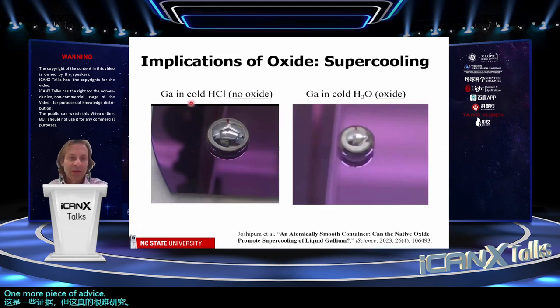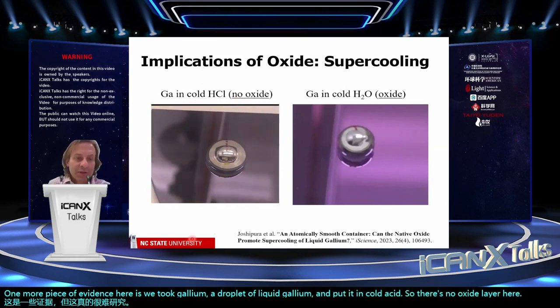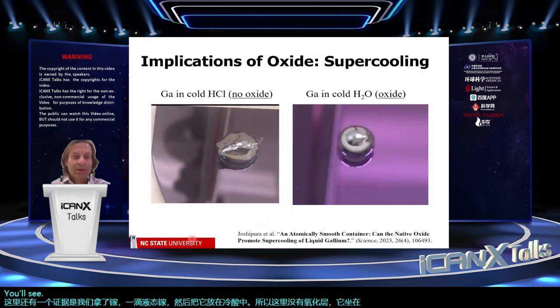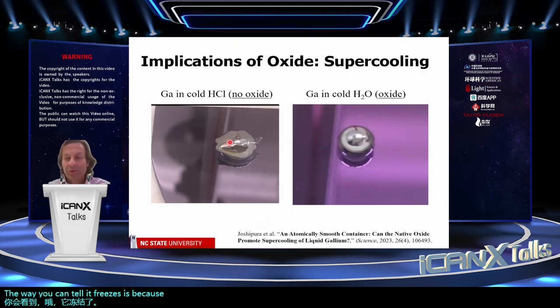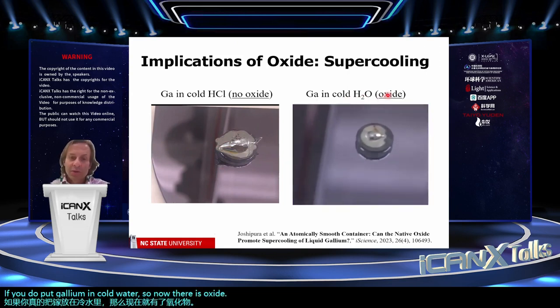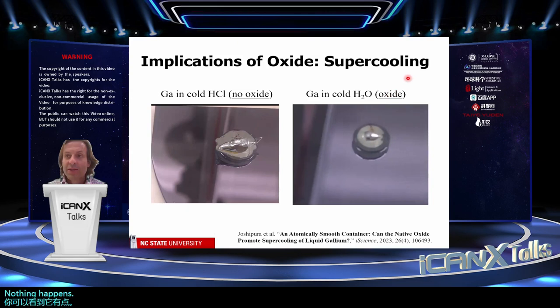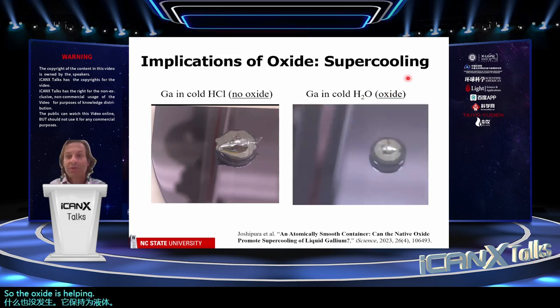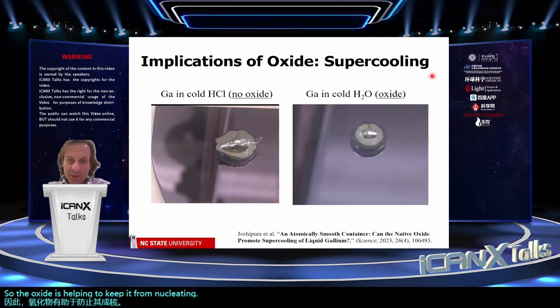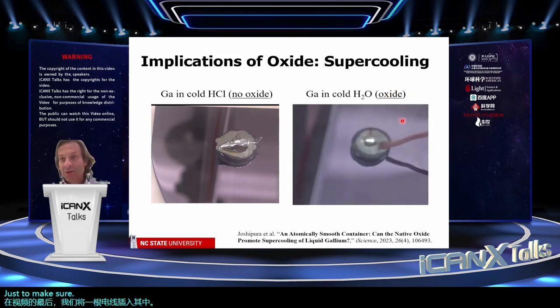One more piece of evidence here is we took a droplet of liquid gallium and put it in cold acid. So there's no oxide layer here, and it's sitting on a wafer. Here it's sped up. You'll see, oh, it freezes. The way you can tell it freezes is because it forms a crystal, and so it's no longer spherical. If you put gallium in cold water, so now there is oxide, nothing happens. It stays as a liquid. So the oxide is helping to keep it from nucleating. At the very end of the video, we stick a wire into it just to make sure it's a liquid. And actually, when you stick the wire in, it will nucleate and freeze. So that's actually our trick to get it to freeze.